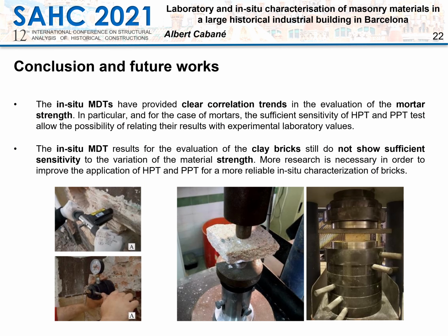We are going to present now the conclusions and the future work that we obtained in this research. The in situ minor destructive techniques have provided clear correlation trends in the evaluation of the mortar strength. In particular, in the case of mortar, the sufficient sensitivity of the HPT and PPT tests allows the possibility of relating the results with experimental laboratory values. The in situ minor destructive technique results for the evaluation of the clay bricks still do not show sufficient sensitivity to the variation of the material strength.